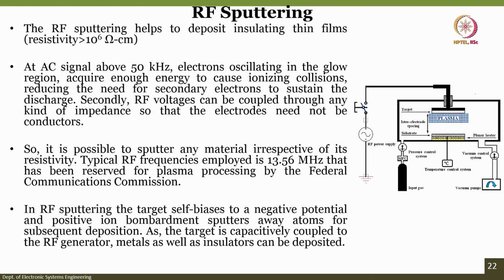In RF sputtering, the target self-biases to a negative potential and positive ion bombardment sputters away atoms for subsequent deposition. As you can see, here is a substrate, and the substrate is generally temperature cooled. There is an effect of temperature cooling and temperature heating. So, heating the substrate has an advantage, cooling has an advantage. Depending again on what kind of application you are looking at, sometimes you heat the substrate to a certain temperature and you will have better polycrystalline films.